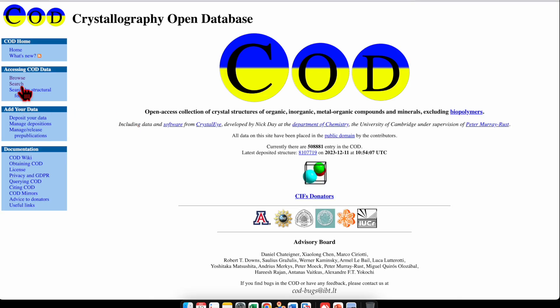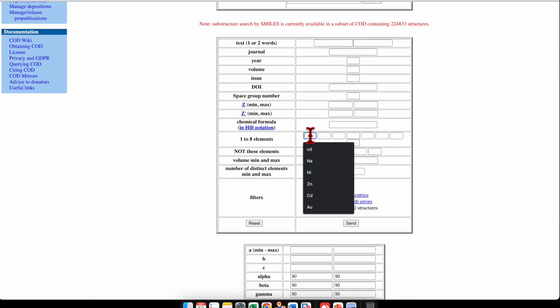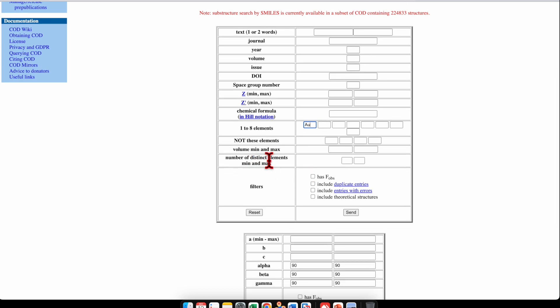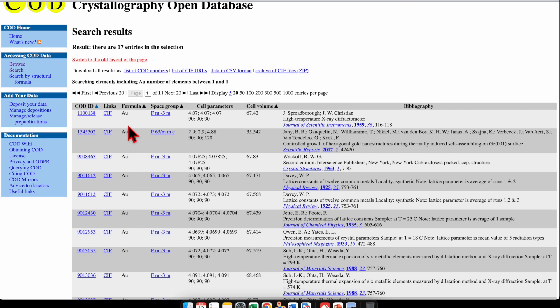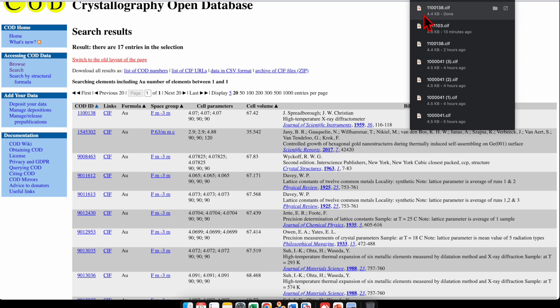Here you will find an option for search — click over here. Then go down and type the element name: Au. Set the number of distinct elements minimum and maximum to just one, then click Send. You will find a list of CIF files reported by different research groups. In the case of Au, the space group is Fm-3m, that is a face-centered cubic structure, with its cell parameters.